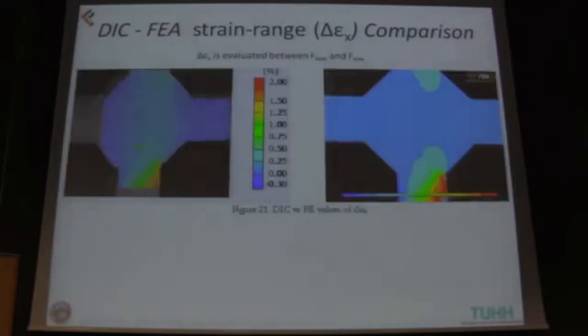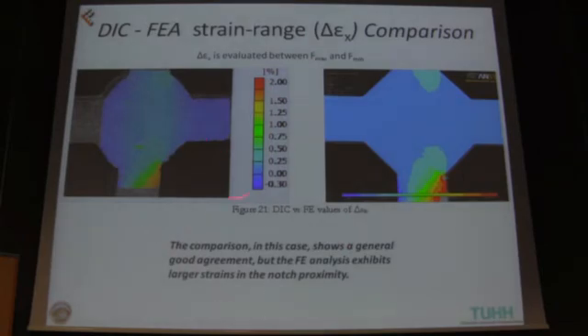For this reason, another comparison was made in order to avoid the residual stresses, and so the comparison was made between F max and F min. As we see from this comparison, there is a general good agreement, even if there is still some difference, because the finite element model exhibits larger strains in the notch proximity with respect to the DIC measurements.